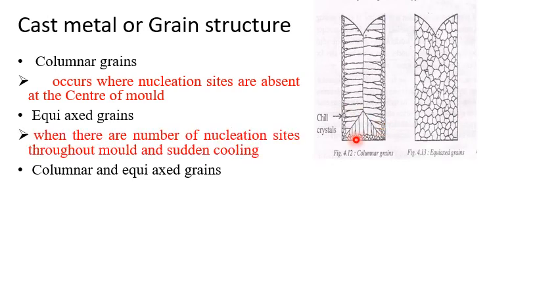Then next is the equiaxed grains. You can see it here. This is where there are a number of nucleation sites throughout the mold and sudden cooling. So this is something like a homogeneous nucleation. There are a number of nucleation sites which are going to form everywhere, and the sudden cooling will not allow the grains to grow, and they will freeze at that moment, forming a fine grain size.